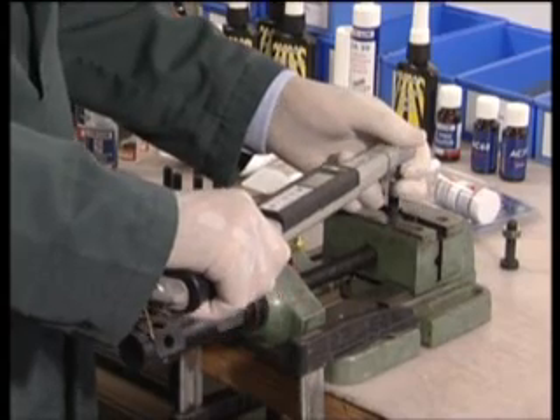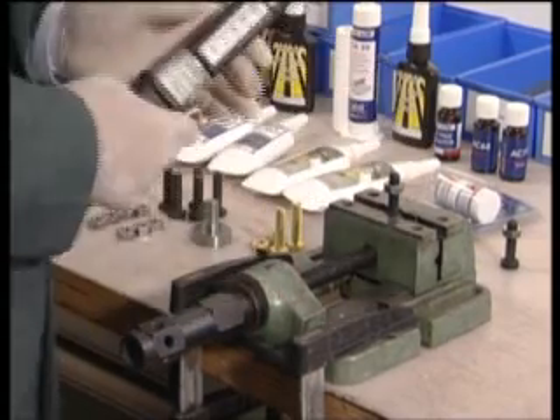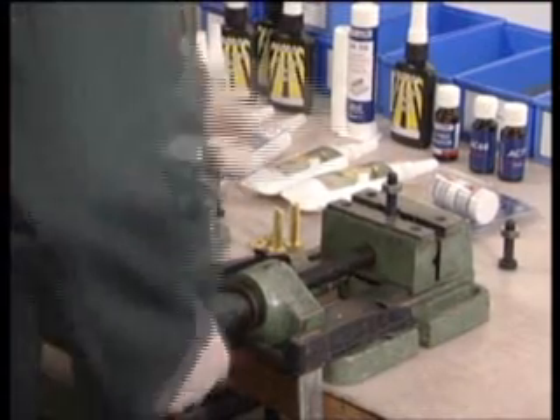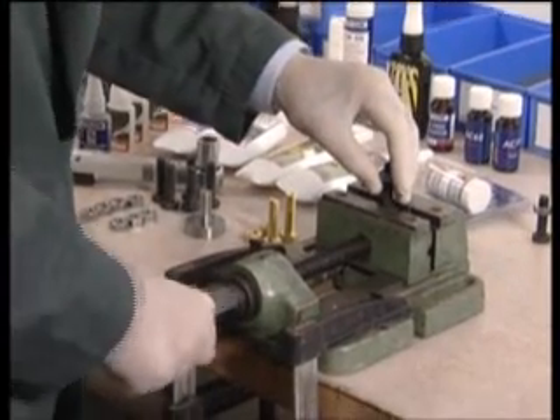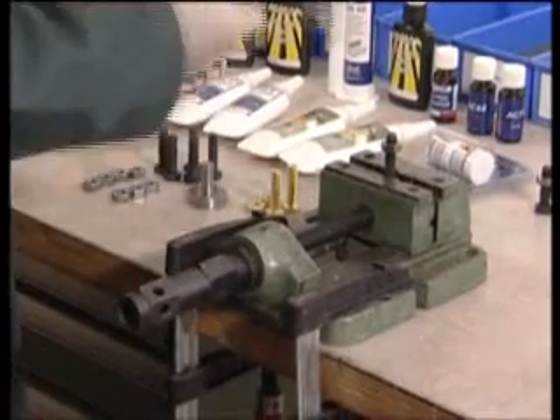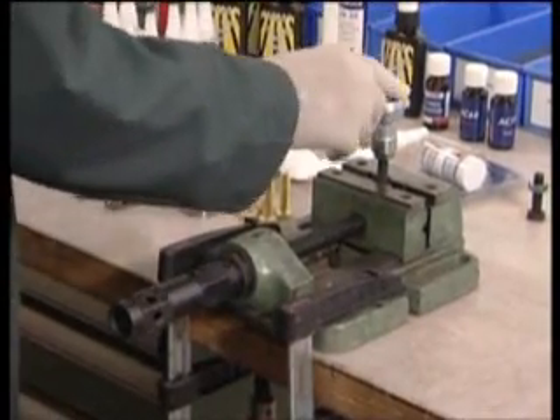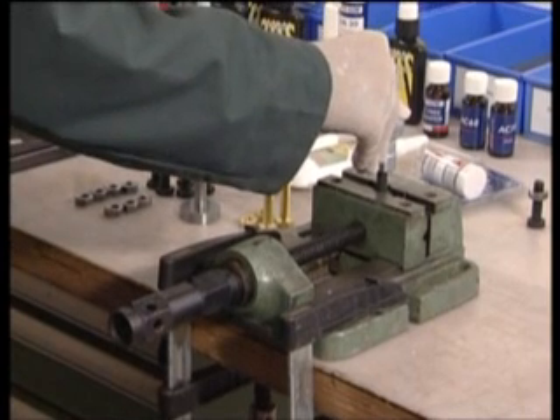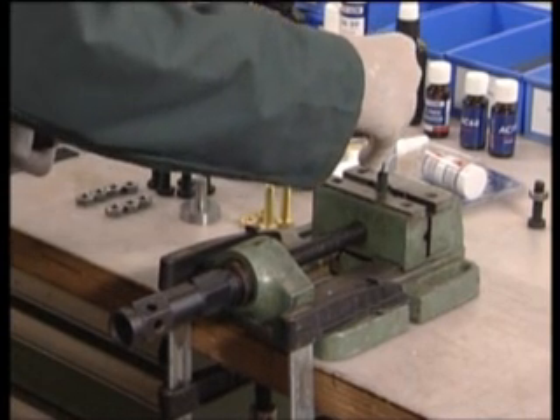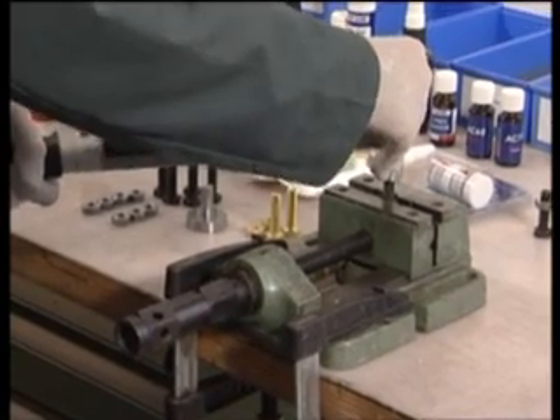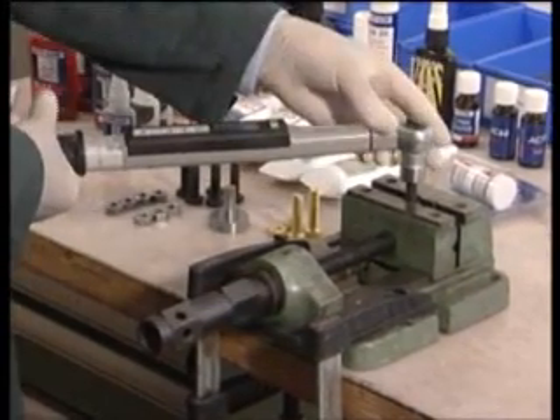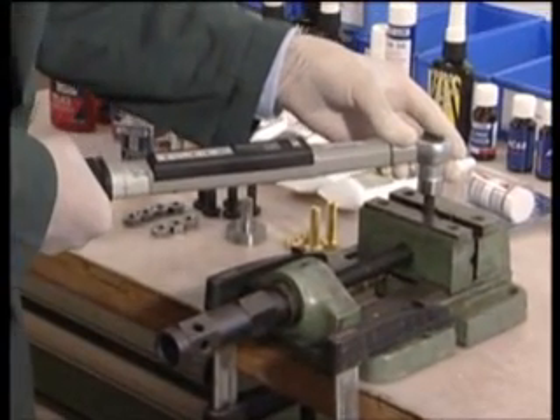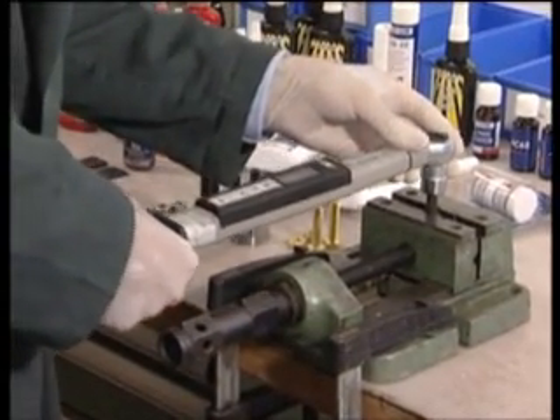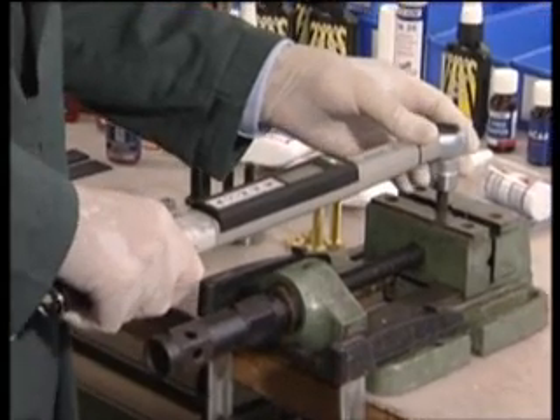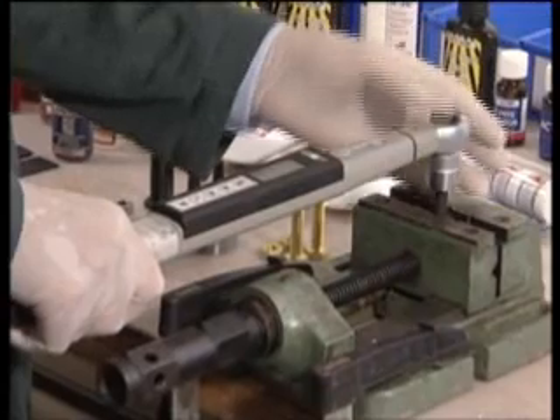Now I'm going to disassemble a high strength product, which is TL70. And as you can see, that's a much higher strength required to remove this product or to disassemble the joint. And also the prevailing torque is much stronger, which means that this product has even more vibration resistance than the previous TL43.